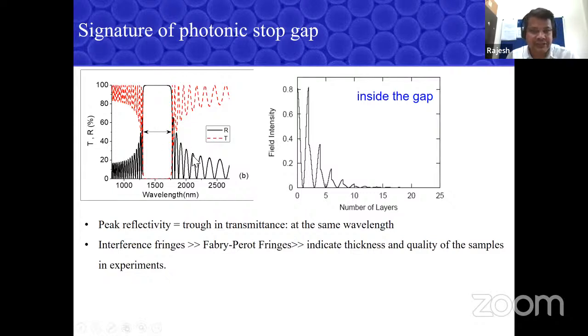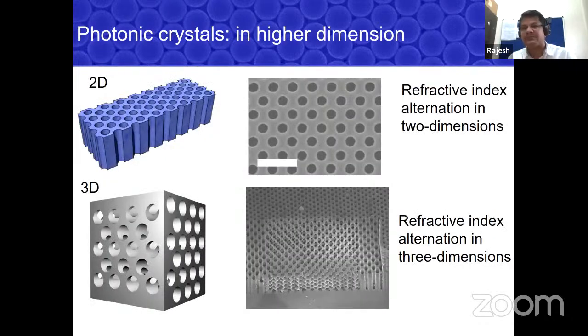Okay, and you get these nice fringes here. These are because of interference, the thin film interference. You have nice fringes, and the fringe width and strength depend on thickness and refractive index, like in any basic optics you studied. So you can estimate the thickness, which is a very nice way to get the sample thickness. I'll show you the real samples later.